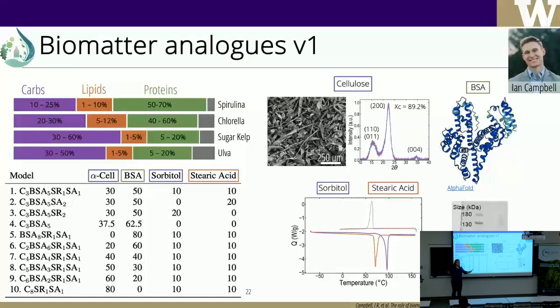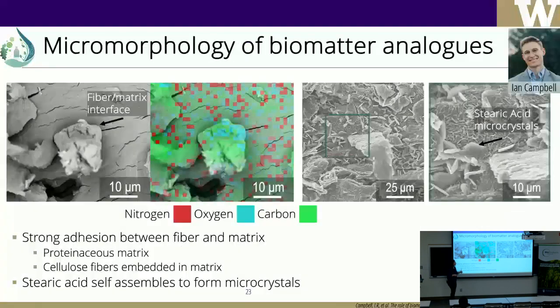And of course, here we're not talking about structure at all, just compositional similarities. So when we start mixing those materials together, it's dry mixing, I think speed mixing actually, before we put them in an extruder and then in a hot press in a variety of conditions. We also do design of experiments there. In all of the conditions, we see the same thing: nothing is enough to actually break up cellulose. It will not defibrillate. It will stay as agglomerated as it is, so it's a very, very large fiber.